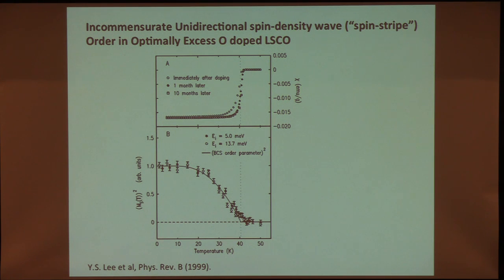This is one of the cleanest of the cuprates. This is oxygen-doped lanthanum cuprate. And what you see here is the magnetic susceptibility as a function of temperature. So you see a very nice superconducting transition temperature here at 42 Kelvin. And this is a neutron scattering study. This is an incommensurate spin density wave Bragg peak that's measured by neutron scattering, which turns on in a rather order parameter-like way.